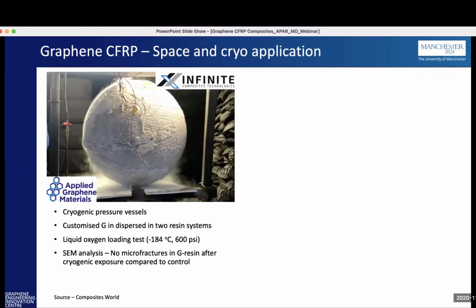And what they found was with a non-graphene material, the vessel would fail after 10 minutes due to low temperature causing microcracking. So the minus 184 degrees C and the pressure of 600 psi would cause microcracking in non-graphene material. When they added graphene to it, under SEM analysis, they noticed there was actually no microfractures at all, which enabled them to keep the pressure vessel safe. So it's a really good project, that one. It shows what graphene can actually do.